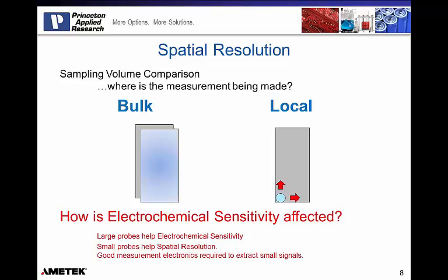So let's look at it the other way. What if I take that probe and I start making a smaller and smaller diameter probe? Your spatial resolution is increased. But as that probe gets smaller and smaller, the current being measured at that probe becomes smaller and smaller, and this dictates that the change in electrochemical activity at the sample surface only creates a smaller percentage change being measured by that probe. Additionally, there are more complications. As we stated earlier, we want to be about 2 to 4 probe diameters away from the sample surface. So if we're working with a probe that's only 10 microns in diameter, we need to be 20 to 40 microns away from the sample surface instead of the 50 to 100 microns that a 25 micron probe would allow us to be.